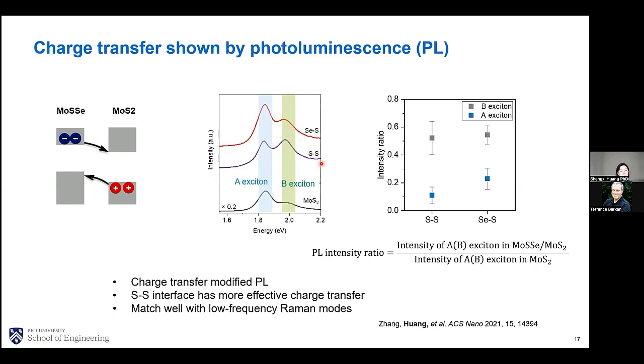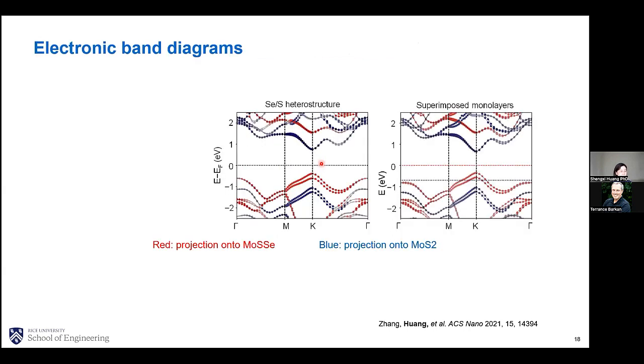Now these results can also be explained using DFT calculations. If we look at the electronic band diagrams, here I show the Se/S heterostructure. The red dots show the projection onto MoSSe, and the blue dots show the projection onto monolayer MoS2. You can see the band structure is essentially the same as the superimposed monolayers. So that means when we form the Se/S interface, the two layers barely talk to each other and the band diagrams just do not change.